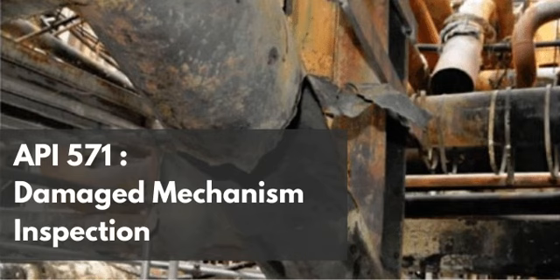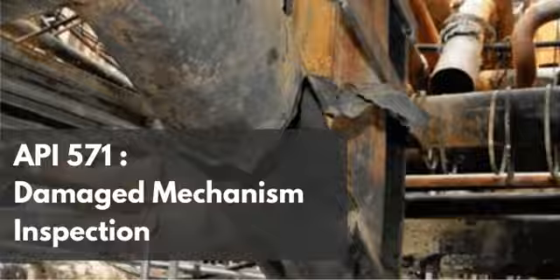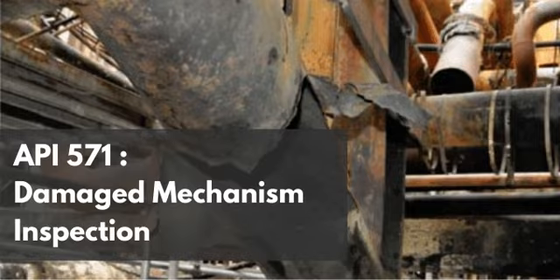Precisely. As the crack opens up the grain boundary, the oxide forms inside the microscopic void. Because the oxide requires more physical space, it acts like a microscopic crowbar, exerting immense localized physical pressure against the crack walls. Yeah, it's essentially manufacturing its own mechanical stress. That's crazy. You have the residual stress from the welding pulling the crack open, and now you have the physical bulk of the oxide wedging it further apart from the inside. Right, which increases the local stress intensity factor at the crack tip. That exposes fresh grain boundary, which then oxidizes, creating more volume, driving the wedge deeper. It's just a terrifying self-feeding loop of structural degradation. It is. It's a continuous autocatalytic cycle.